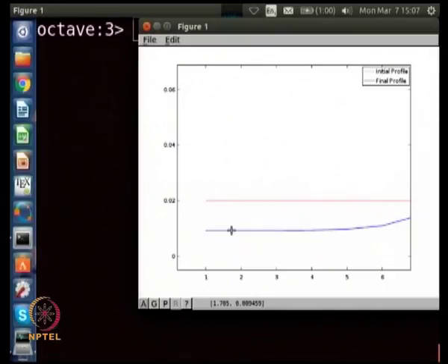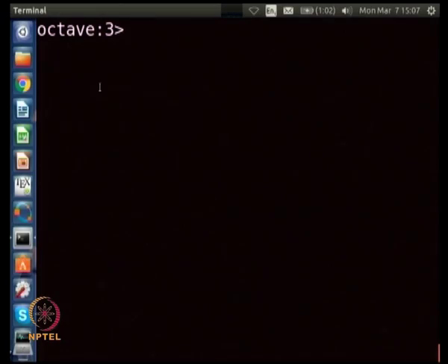So, if you equilibrate it, after a while it will come to 0.008, and the other profile will also go to 0.008. But 64 is a small system on which I have taken a very large precipitate, that is the reason why the diffusion fields are overlapping. So, it is not really equilibrating, but in the case of 10, on the other side also, you will see that on the matrix side the composition shifts by the same amount.